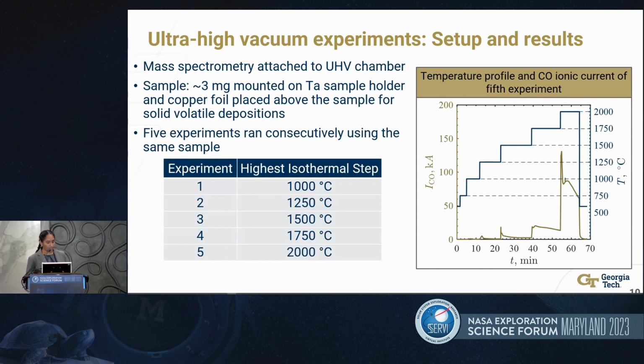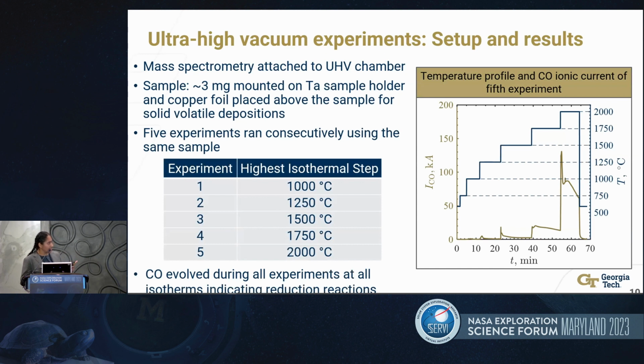temperature. So in all experiments, the sample was first heated to 750 Celsius and then heated up in increments of 250 Celsius all the way up to its highest isotherm, as shown in the table. The results for the final experiment are shown in the plot. So the key takeaway from these results is that CO evolved during all experiments at all isotherms, indicating reaction, except at the 750 isotherm in the last 2 experiments due to completion of volatile evolution.